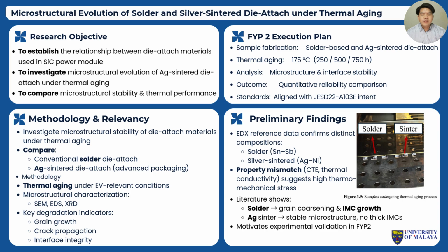At the current stage of the project, preliminary findings are based on reference material data and reported studies. EDX reference data confirms clear compositional differences between solder-based and silver-sintered die attach, while material property mismatch such as CTE and thermal conductivity suggests high thermomechanical stress during operation. Literature consistently shows that solder joints suffer from grain coarsening and intermetallic compound growth, whereas silver-sintered joints exhibit a more stable microstructure without thick brittle IMC layers. These findings strongly support the research direction and motivate further experimental validation.